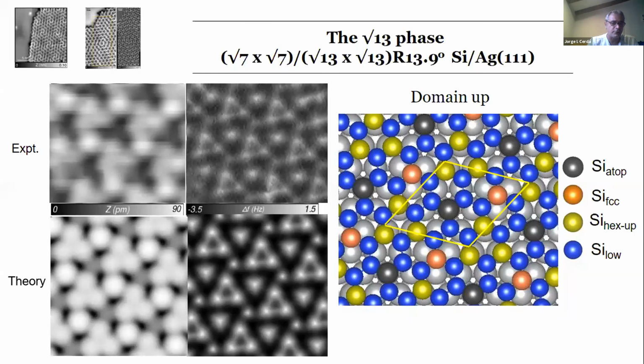When we did the simulations, we actually obtained a very good agreement again with the experiment. We can reproduce all the features, even the relative intensities, both for the STM and for the AFM images. We can actually see the 2 bumps, one which is brighter than the other one.